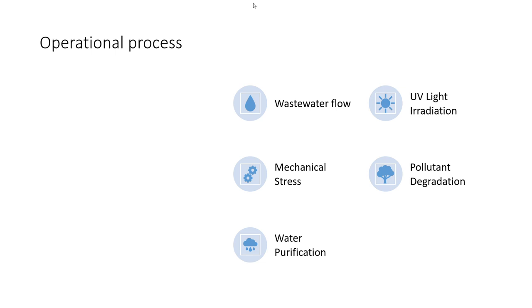Ultraviolet light irradiation: ultraviolet light is applied to the thin film, generating electron-hole pairs in the tin oxide layer. The photocatalytic reactions initiate, producing hydroxyl radicals. Mechanical stress is applied to the barium titanate layer. The piezoelectric effect generates electric charges, enhancing charge separation. Then pollutant degradation occurs due to the reaction of hydroxyl radicals with organic pollutants, which will degrade them. Enhanced photocatalytic efficiency is then aided by the piezoelectric field. Then the treated wastewater flows out of the chamber and pollutant concentrations decrease, achieving water purification.